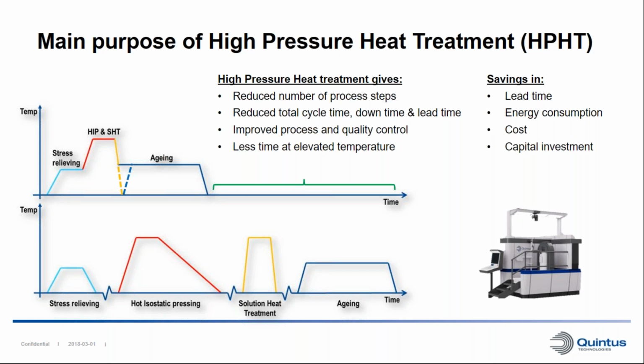So with high pressure heat treatment, we get savings in lead time. The conventional route has to be performed in at least 2 different equipment, the HIP and a heat treatment furnace. If you're sourcing this service externally, this might be 2 different sites or even more different sites. So you have to ship the material back and forth to get these processes done.